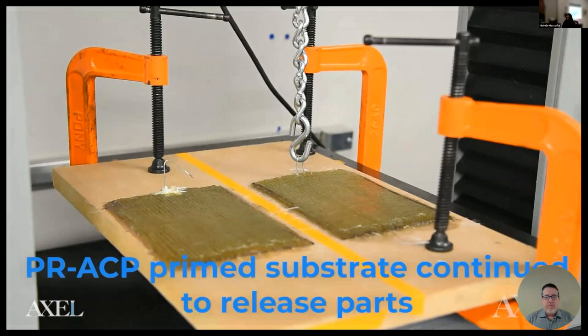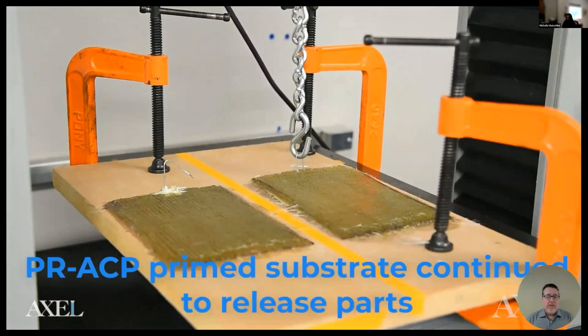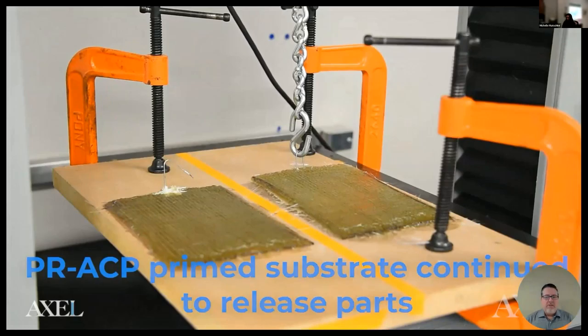And normally on a substrate such as high density fiberboard, you would apply more coats of primer and more sealer and release. It's done in a lab setting to try to accelerate showing the differences. If we put 5 coats of the primer, 2 to 3 coats of sealer, 5 coats of release, it could take 30 or 40 pieces to sometimes start seeing where one system is letting go or starting to see failure modes where the other one is continuing to go.